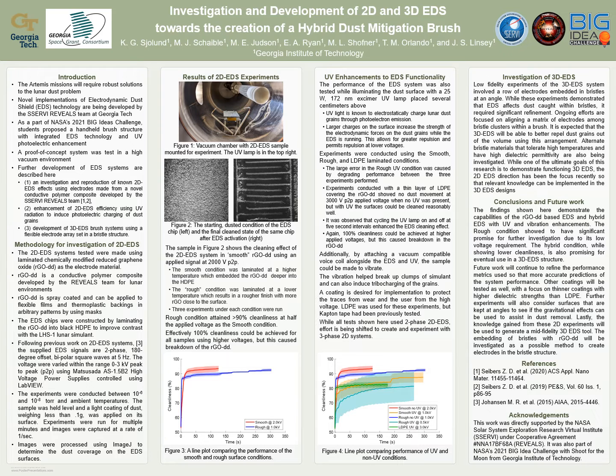To investigate the effect of combined EDS and UV radiation, an excimer UV lamp was used. The smooth and rough conditions EDS samples were tested under the same conditions with 5-second pulsed UV exposure. Figure 4 shows the cleanliness achieved from all experiments. Note that the UV exposure halved the required voltage necessary to achieve high levels of cleanliness. An additional condition, with LDPE laminated on top of the RGO sample, was also investigated as a coating layer will be required for practical implementations of EDS.